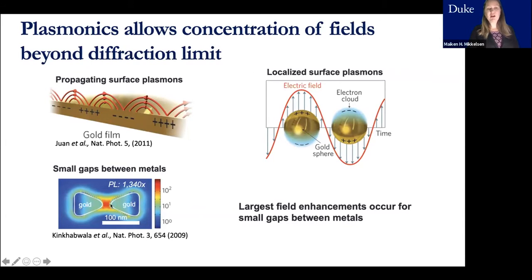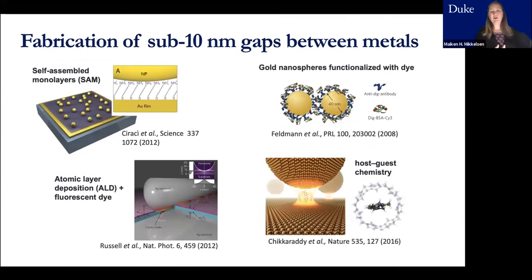So then the question becomes, how do we actually realize this experimentally? These are made using electron beam lithography, and making these tiny gaps is very challenging, and you're really reaching the limit of electron beam lithography. You will not be able to do this with single nanometer precision, and you will just smear out effects. So what I started thinking about, and others in the field were thinking about as well, was how can we make very tiny gaps between metals, in particular sub 10 nanometer gaps, with a resolution on the single nanometer scale.